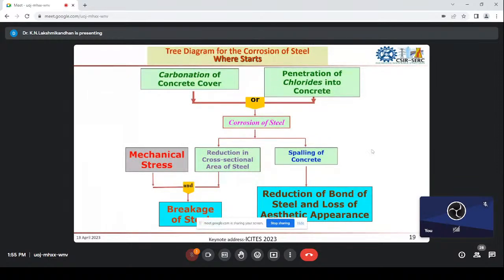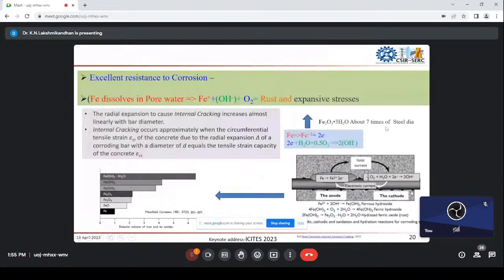So in both ways, what we are seeing is that the carbon dioxide or the chlorine does not directly impact the concrete. It only reacts with the calcium hydroxide, which is normally called the passive protection layer. Once the passive protection layer breaks down, then the corrosion starts. So this way, carbon dioxide or chlorine contributes to the development of corrosion.